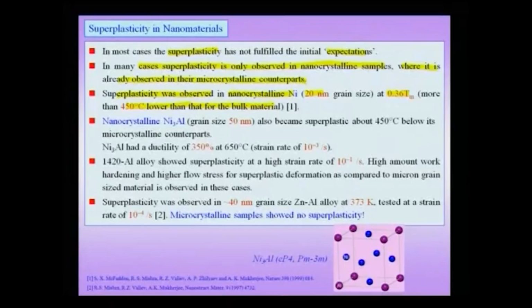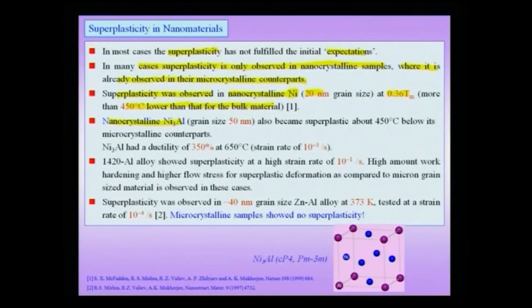And the first one is a case of nickel, wherein in the 20 nanometer grain size sample superplasticity was observed more than 450 degrees lower than that for the micron grain sized or larger grain sized bulk counterpart. So, this is very, very interesting. In nanocrystalline Ni3Al, and you know Ni3Al is an intermetallic which has an L1_2 structure, the unit cell of a typical Ni3Al is shown here at the bottom of the graph. And when compared to the disordered alloy, you would notice that the Burgers vector is larger in this structure.